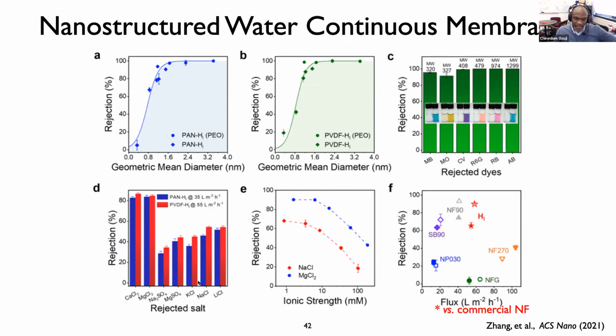We looked at salt rejection in these materials, and we can see data here that is quite typical for nanofiltration membranes, quite strong rejection of divalent salt species relative to monovalent species, and the characteristic fall off in that rejection that you expect as you increase the ionic strength of your feed stream due to electrostatic screening. What for us was very attractive, though, was the performance of these membranes when considered against commercial nanofiltration membranes. And so we did low pressure nanofiltration testing, and we benchmarked the performance of our membranes here, shown in red, for divalent and monovalent salts, open and closed symbols respectively. And we benchmarked those membranes against a series of commercial nanofiltration membranes.